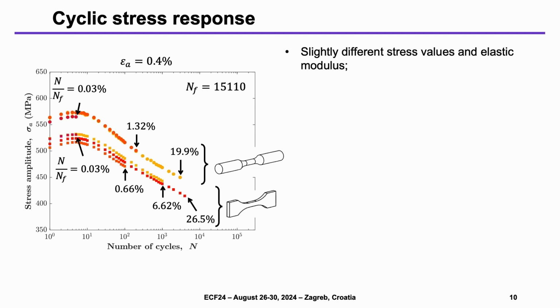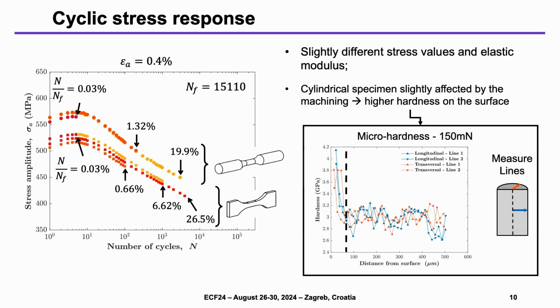As you can see, there is also a slightly lower stress value for the flat specimen, and also a lower elastic modulus, which is not visible here. And this is due to a high ratio between porosity and cross-section area of the flat specimen. In addition to that, we also observe a slightly higher hardness on a surface layer of the cylindrical specimen due to the machining, and this could also have an influence on the mechanical response.